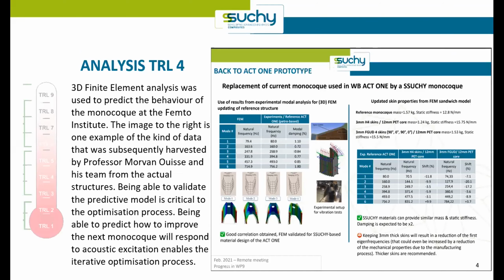So here you can see some of the work that was done by the Femto Institute, and you can also see that this was now looking at the monocoque and predicting exactly how it was going to behave. So we had moved now from TRL3 to TRL4, and as a result of this information that we've derived back from the Femto Institute, we were able to try and aspire to get the amount of fabric into the mold, but it was found that trying to get as much as what was suggested was quite challenging, because the mold was difficult to close. So we had to start to, at this stage, come up with compromises or different alternative methods of creating the dry pack before it was infused.